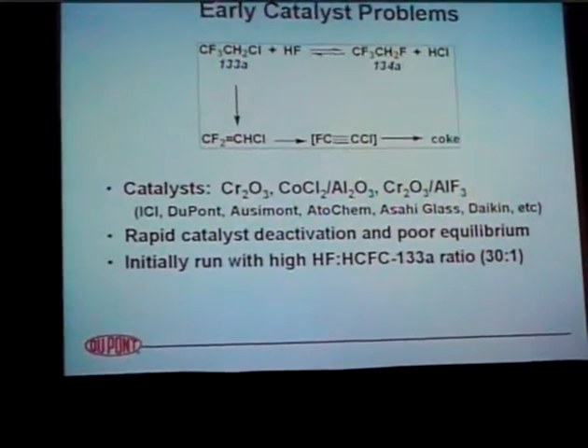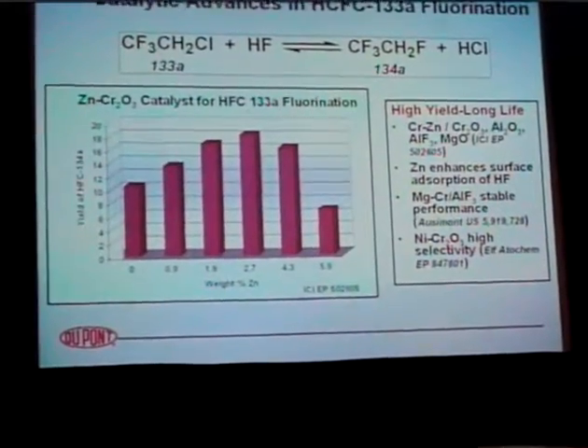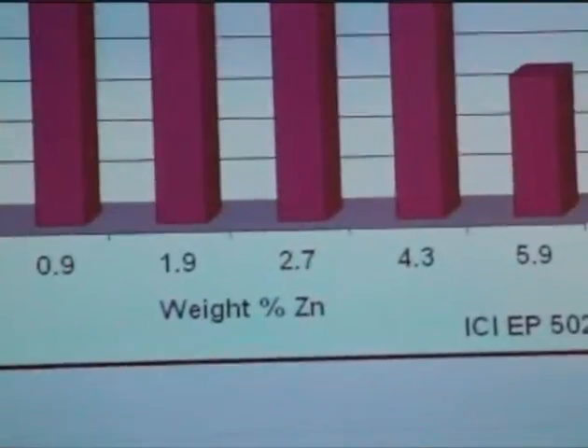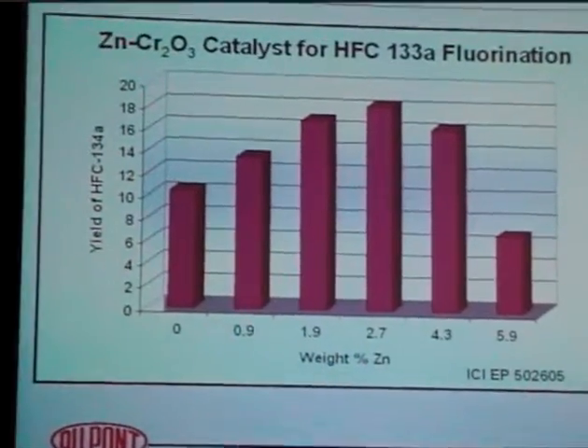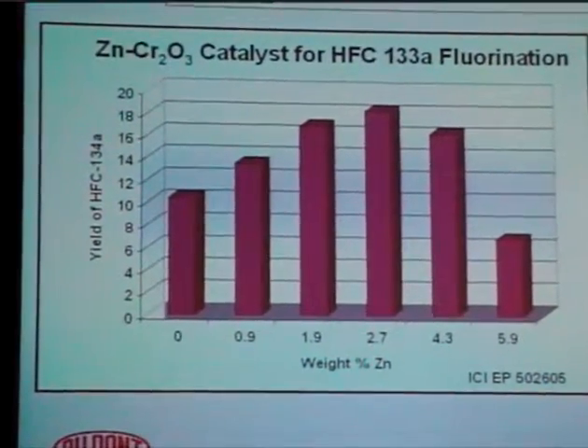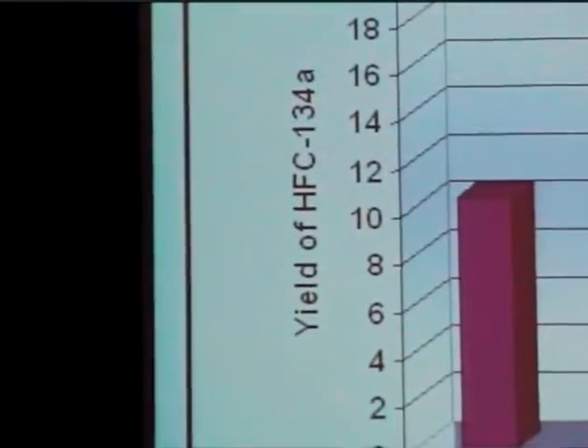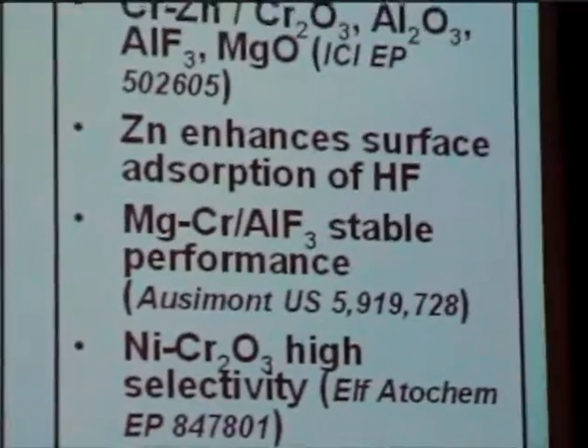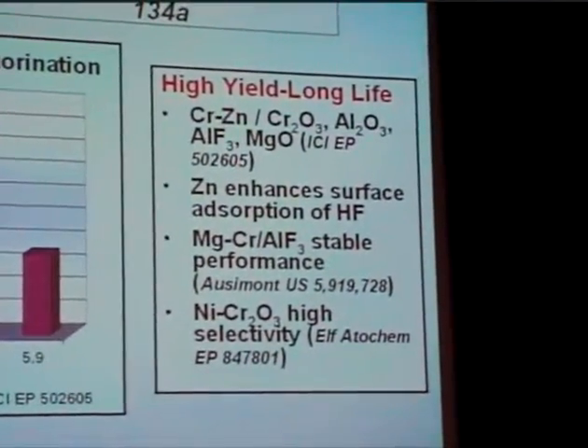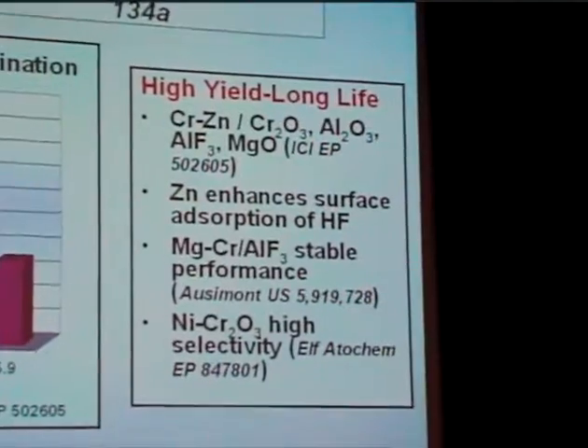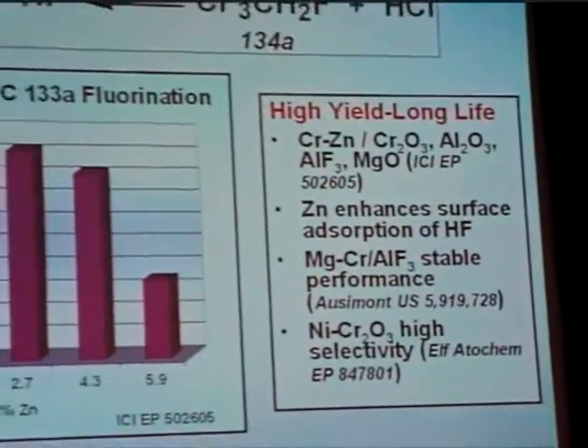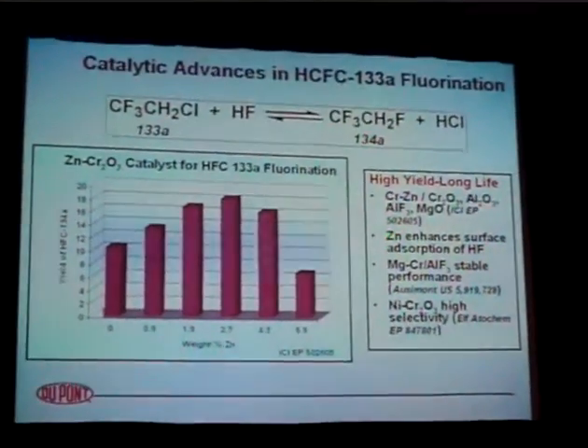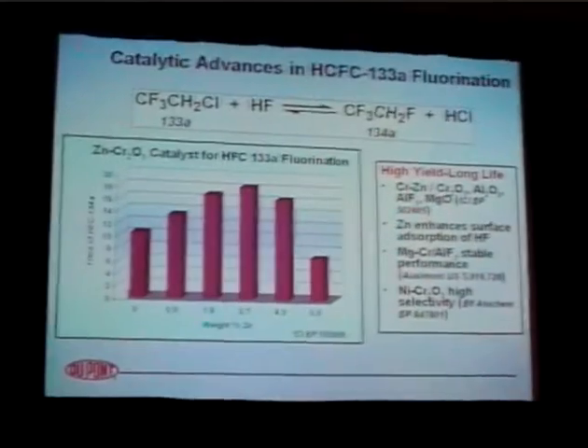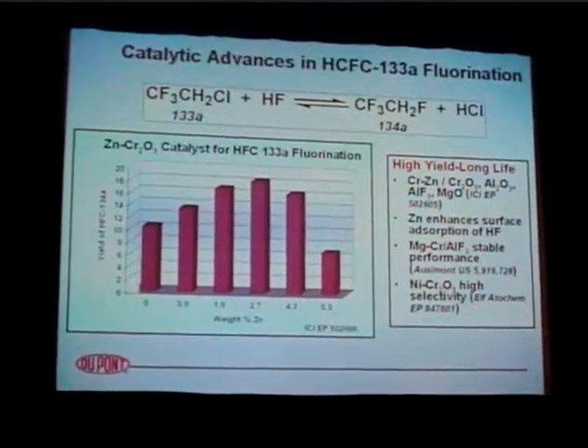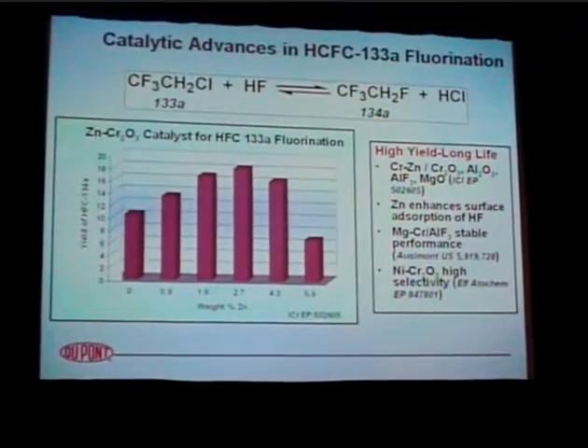And since that time, there have been some major advances in improving both of these issues. So we're looking at the top reaction there, the 133a plus HF, to exchange that one fluorine to make tetrafluoroethane. If you look down in the graph below, you can see some data showing the effect of promoting chromium-3 oxide with zinc at different levels. This is a patent by ICI. And you can see there's an optimum there at around 2.7% zinc in the chromium-3 oxide. And by adding that zinc in there, it has a big effect on improving the yield in the process, and actually we cut way down on the amount of HF that's fed to the reactor, because it's believed that the zinc is increasing the local concentration of HF around the chromium and causing higher conversions to take place.